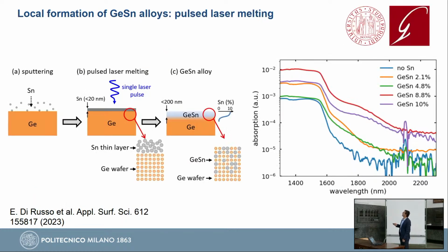And so for doing this, we are actually working together with the team here of Enrico Napolitani. And the technique we use is pulse laser melting. So again, if we want to trick thermodynamics and not fall into the equilibrium case where we have the two phases separated, we need a process which is very strongly out of equilibrium. And I think this is really the case with pulse laser melting, because what happens in this kind of technique is that, for example, you start with germanium, you sputter on top a metallic layer of tin, so this would be an amorphous material, and then you heat it hard with a laser, which melts the first few hundreds of nanometers of your system, so the system is completely molten, and it essentially recrystallizes in a matter of a few nanoseconds.